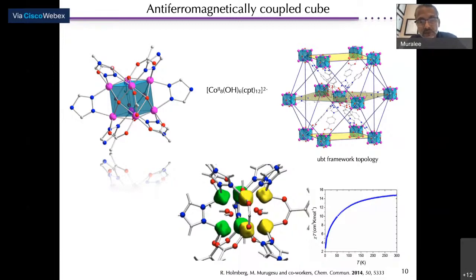And unfortunately, when you look at the spin density of these systems, these 4 cobalt ions are antiferromagnetically coupled. That means the spin centers cancel each other. As you can see in the susceptibility times temperature versus temperature plot, the chi-T plot decreases with decreasing temperature to lead to a singlet ground state. So overall, it's a bit of a dull magnet, or not even a magnet, it's an antiferromagnetically coupled system. Again, it's the biggest disappointment that we had at the time, and we started to get discouraged about carrying out this field of porous magnetic MOFs.